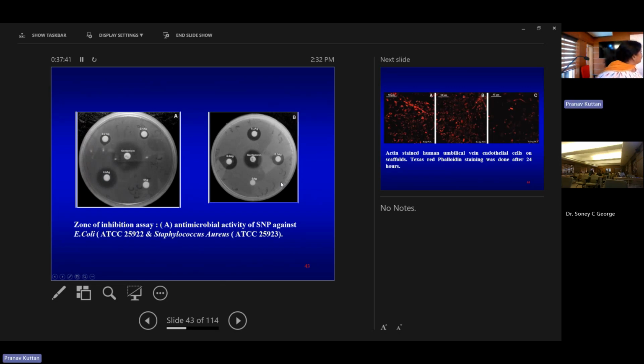And antibacterial activity was found out using the zone of inhibition assay using E. coli and Staphylococcus aureus. As you can see, depending on the concentration, the radius is increasing. That radius is compared with gentamicin. Gentamicin is an antibiotic, so we can compare, and we can see that it is comparable. Though less in diameter, it is showing antibacterial activity.